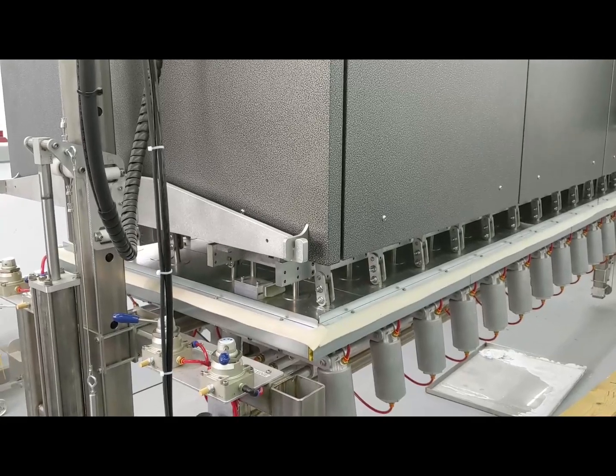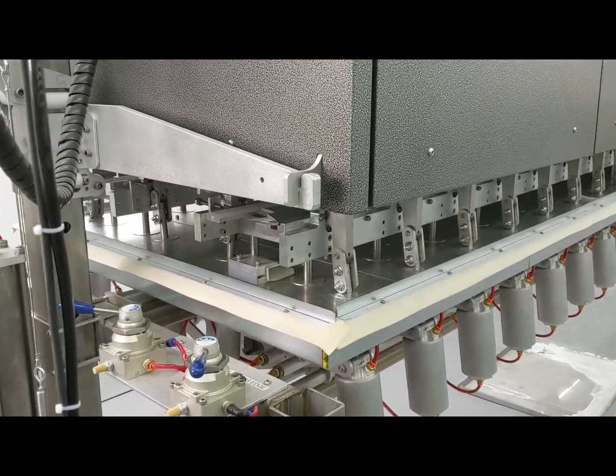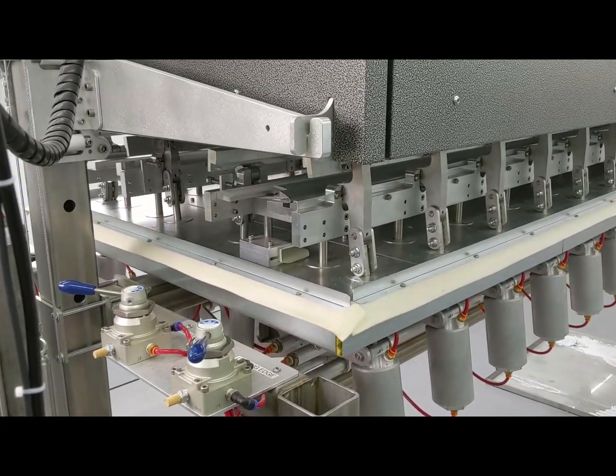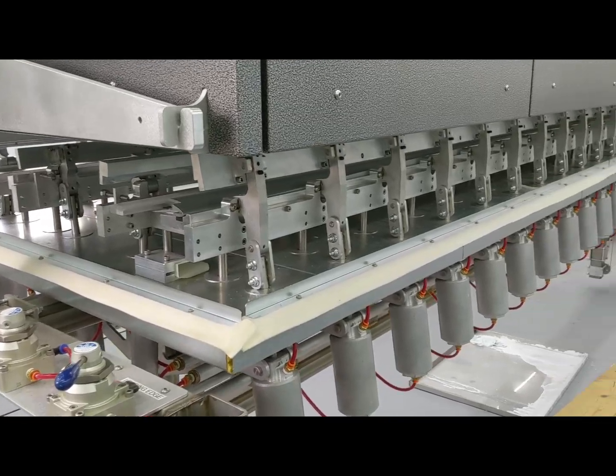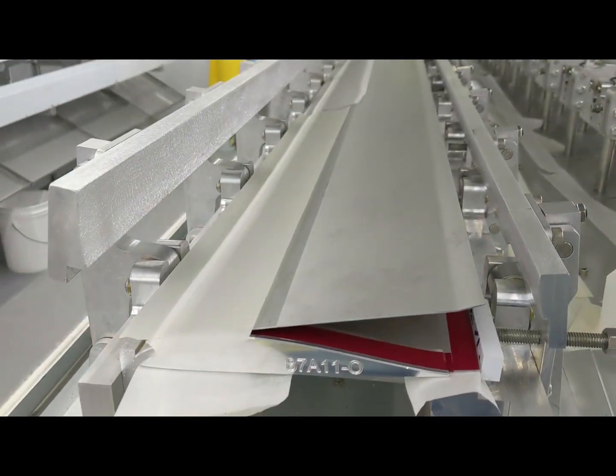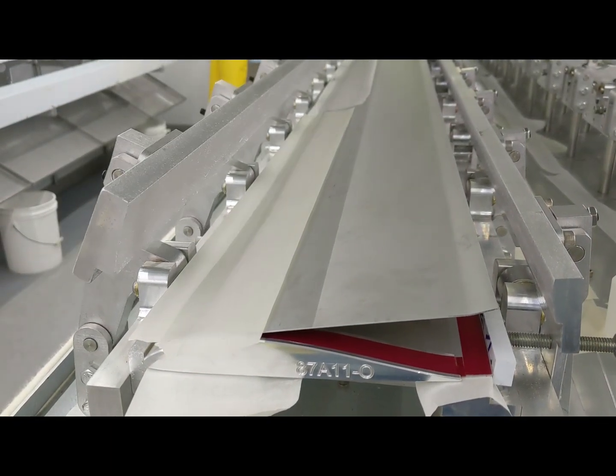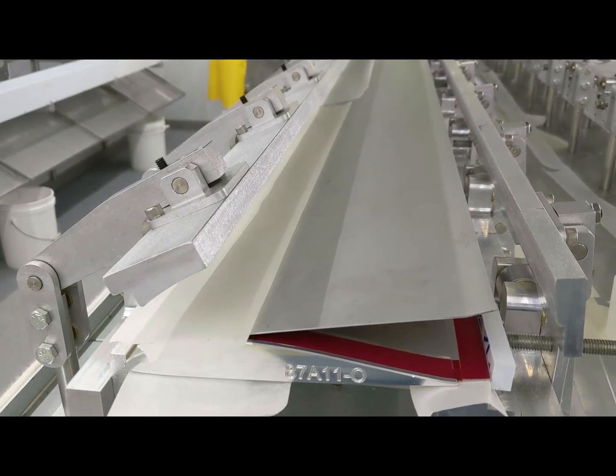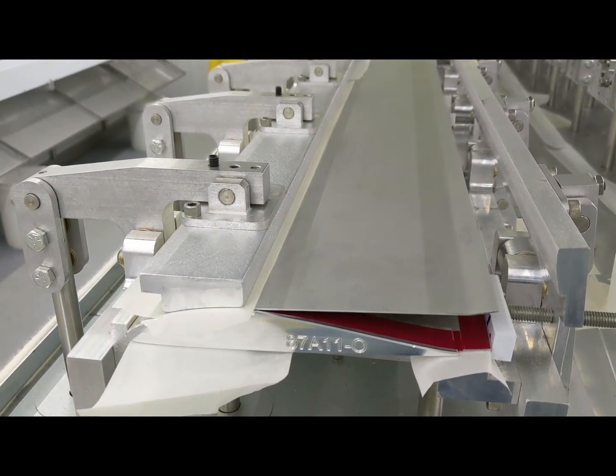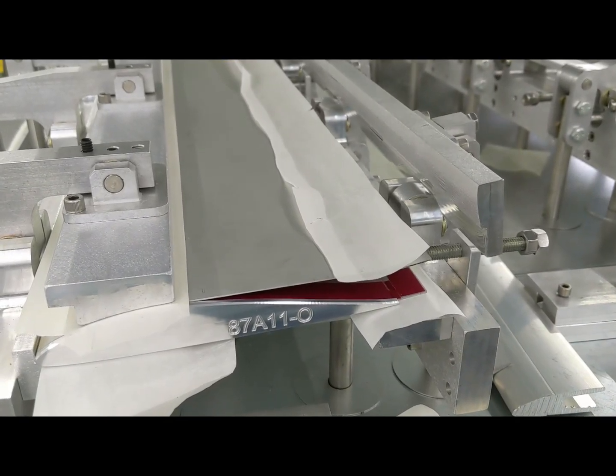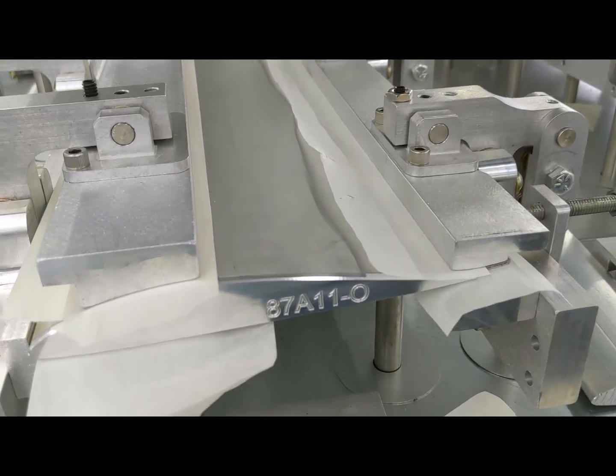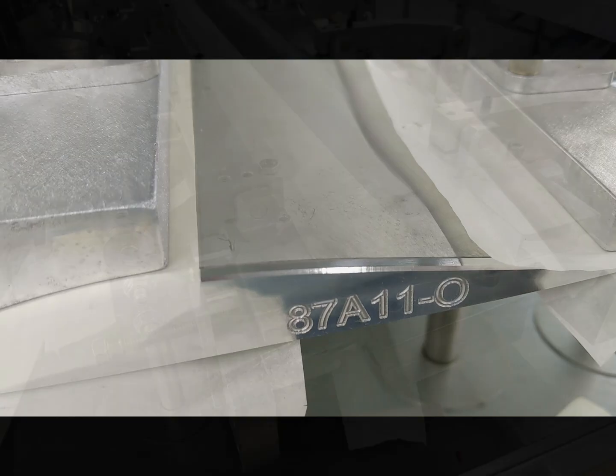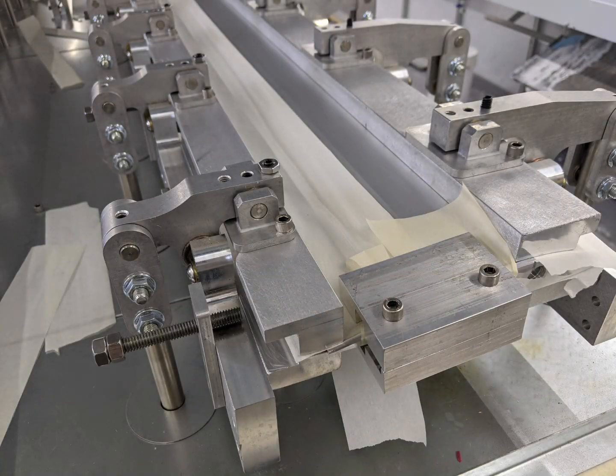The hood opens up to allow access inside the machine. The blades are then placed into the clamp mechanism, which contains the machined profiles. A little silicone-free parchment paper will protect the adhesive from getting on the clamp inserts. You'll see a little jump right there as the twist is imposed on the blade. The trailing edge is then clamped, pulling all the components into precise alignment. End clamp is then added to hold the top and bottom skins to the end caps, and the curing process is ready to start.